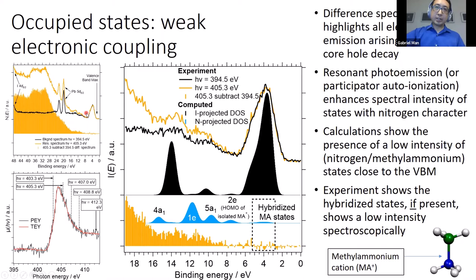If we subtract the black spectrum from the orange one, we can then remove the photoelectron features. And this difference spectrum then represents all of the electron emission arising from nitrogen 1s core hole decay only. So embedded in this spectrum are potentially all of the mechanisms: participator, spectator, and normal Auger decay. The region of interest is closer to the valence band over here. So now we zoom in.